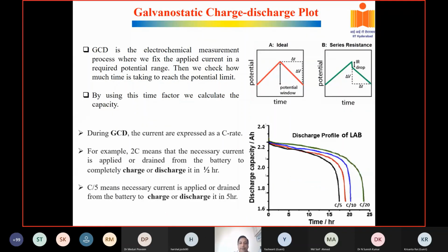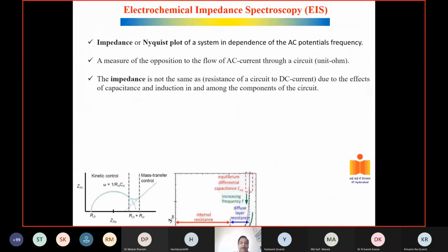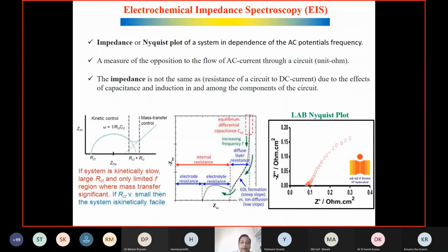First, we do an impedance measurement to understand our electrode resistance and ohmic resistance, because these are very insulating in nature. Fortunately, we have a good electrolyte like aqueous sulfuric acid, which has good conductivity. The electrolyte resistance should be as low as possible. So we do impedance at two different frequencies, and we get electrode resistance, electrolyte resistance, and charge transfer resistance. Other things we also get. Not to worry.